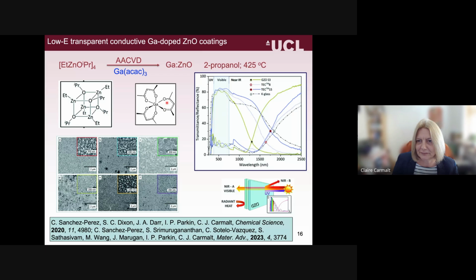So here we made a novel precursor. Zinc oxide is often deposited using diethyl zinc, which is very effective, but it's pyrophoric. Or you can use zinc acac, or you can use zinc acetate. But the zinc acac and the zinc acetate don't give you as good resistivities. So if you recall, I said you need resistivities of about 10 to the minus 4 or lower. And you would typically get resistivities of about 10 to the minus 2 using those precursors.